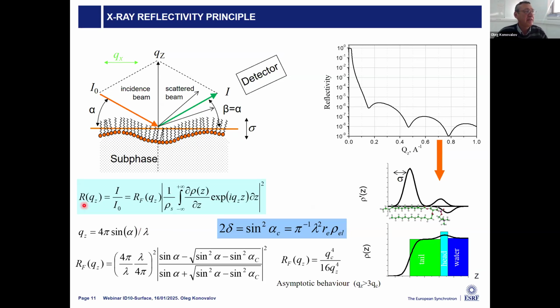So then about reflectivity, if for somebody this is, let's say, a new technique, what is going on? We have a beam going at a certain angle alpha to the surface, and then at the same exit angle, we measure intensity. In this case, as I told, the scattering vector is perpendicular to the surface, and this ratio between incident and measured intensity is a Fourier transformation of electron density multiplied by the Fresnel scattering. And so by modeling and calculation, we can go from the measured curve to the structure. From the periodic oscillations, we can know information about the thickness, about intensity, and information about the distribution of electrons in depth.